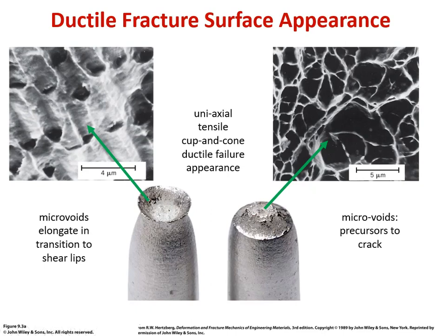So this is, again, our round uniaxial tensile bar. And you can see that the outer circumference is the shear lip, and it's kind of shiny. That has failed ductilely in shear. So you can see it's at a 45 degree angle, and that center portion that looks white and hazy is actually very rough, so it's not shiny. The SEM pictures in both cases show first, on the shear lip, some of those dimples that have been stretched in shear. But the SEM picture on the right is more from the center, and you can see that it is very rough, and you're actually looking straight down on those original microvoids. So the microvoids are actually the precursors to the crack.